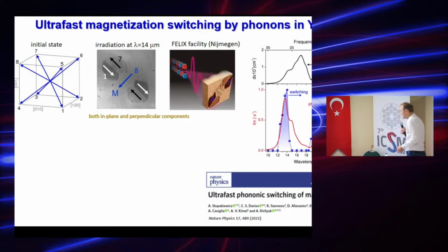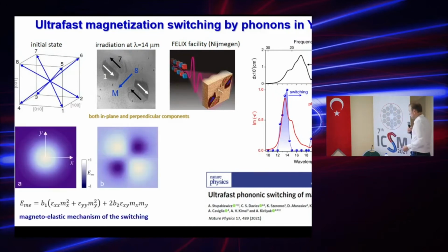If you change the wavelength, the switching nicely corresponds to excitation of the longitudinal optical phonons. We observe it close to 14 micrometers and close to 22 micrometers.